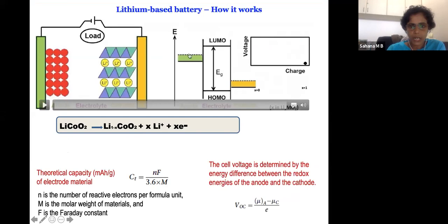So earlier, before the formation cycle, this is the anode side. The chemical potential of the anode was higher than the LUMO, and the chemical potential of the cathode was lower than the HOMO. So now during charging, I want you to see the position of lithium on the anode layers. This is the cathode layer during the charging. And here with the voltage versus charge, what happens to the voltage as we de-intercalate the lithium from the cathode? The voltage keeps increasing. The reason is that the chemical potential difference between the cathode and anode also changes due to the electron transfer from the cathode to anode.